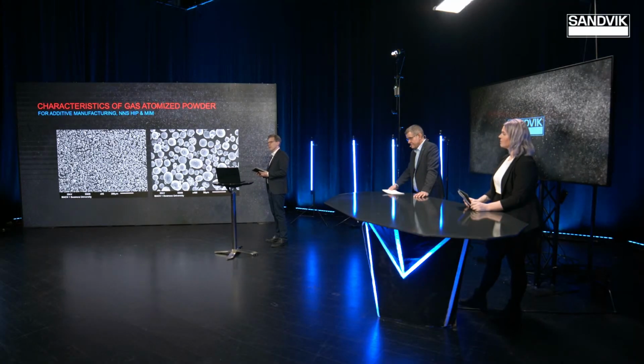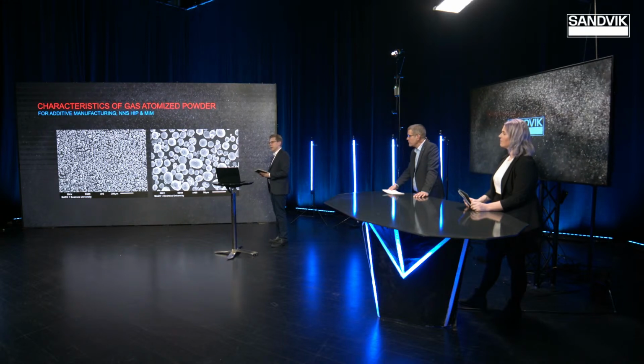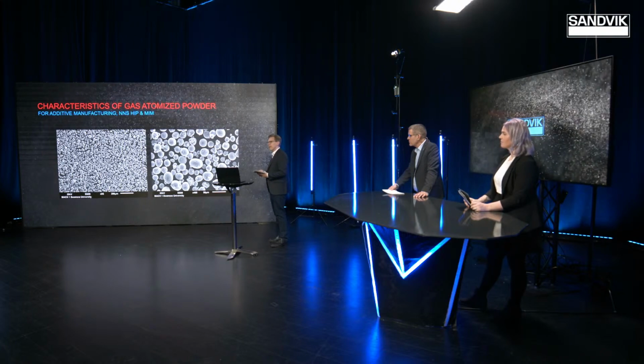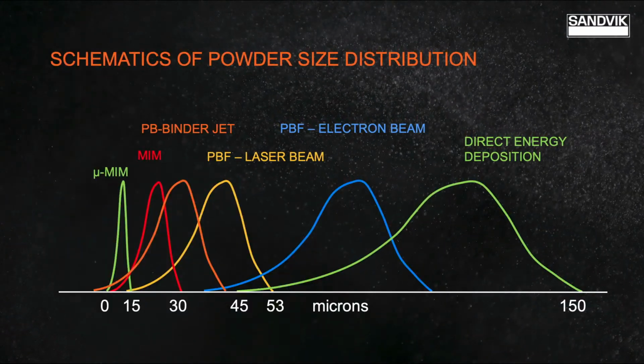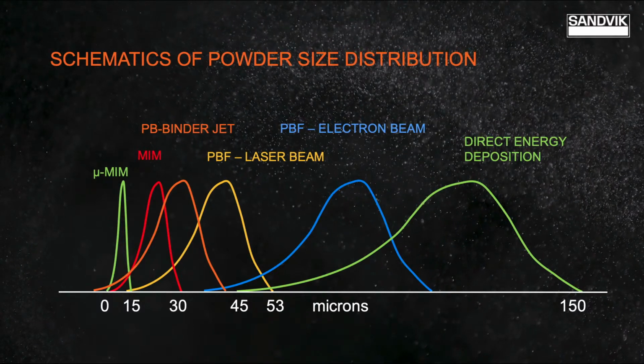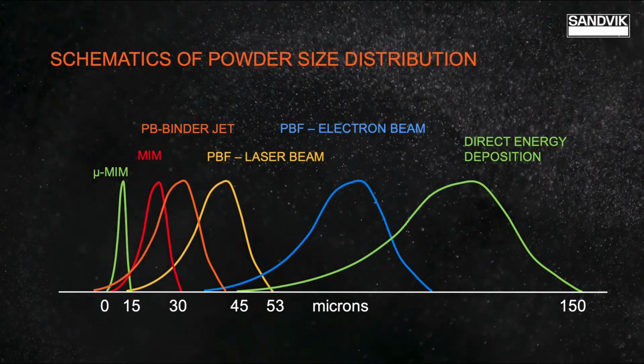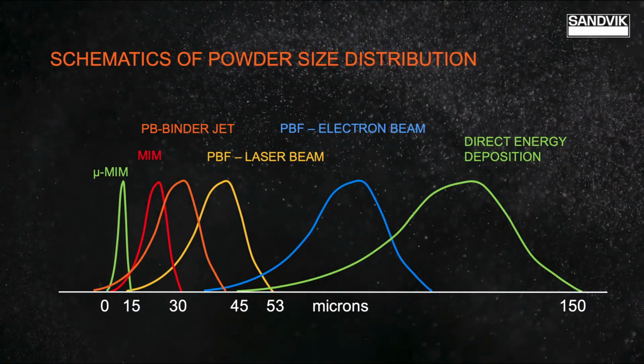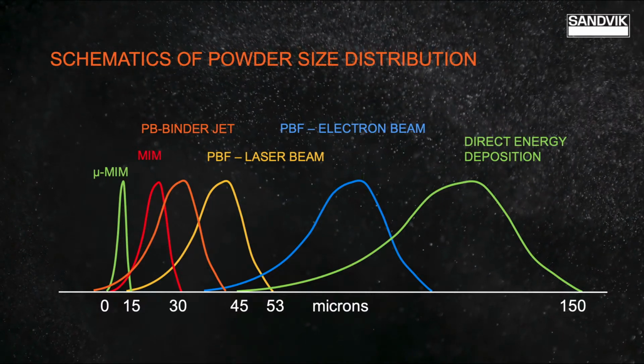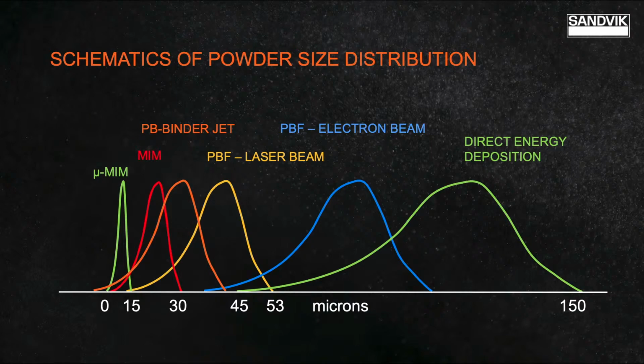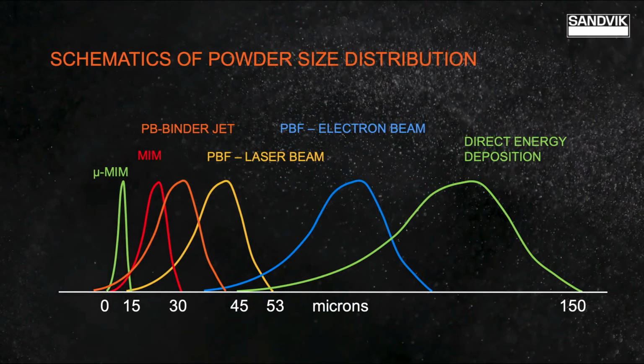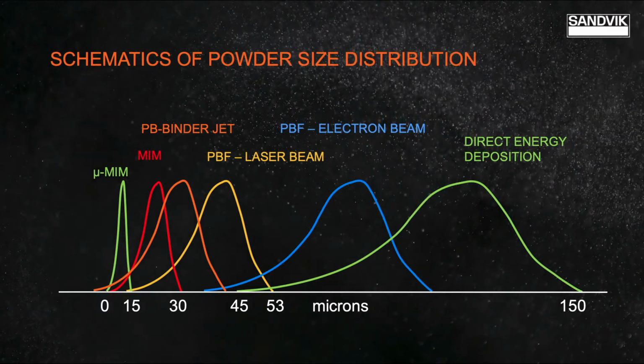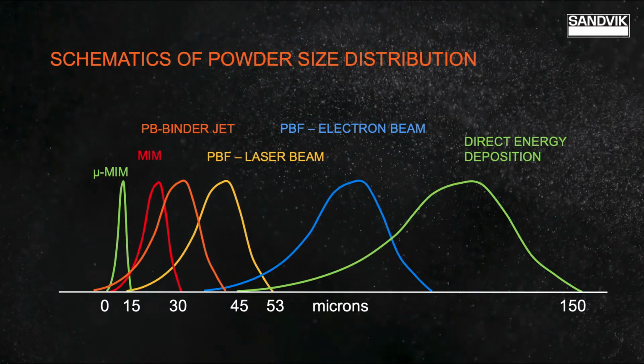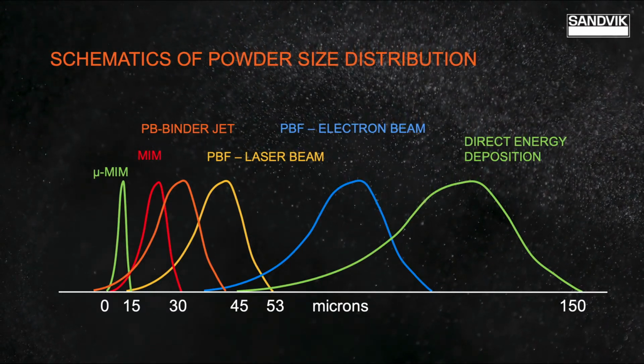And you speak about enhanced microstructures, but what about the size? Does that matter when it comes to which process it's used in? Absolutely. The size is tailored to the different manufacturing processes, in fact. Additive manufacturing has a number of different technologies, from direct energy deposition, where powders are provided from 150 microns to 53 microns, the powder bed fusion processes of electron beam and laser beam, using mid-size fractions, classic sizes of 53 to 15 microns. And then you have new emerging additive manufacturing processes like binder jet, and fine powder technologies like metal injection molding, and even the superfine powders less than 15 microns of micro injection molding.